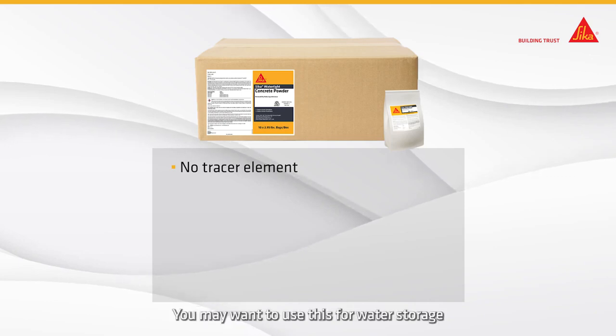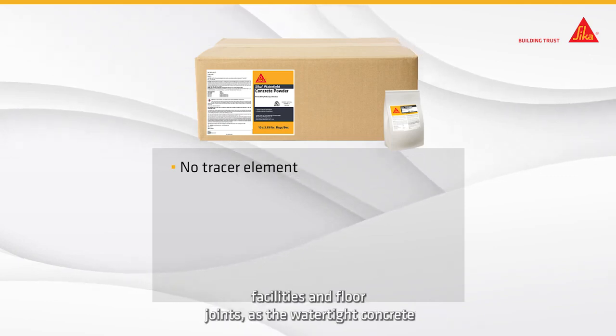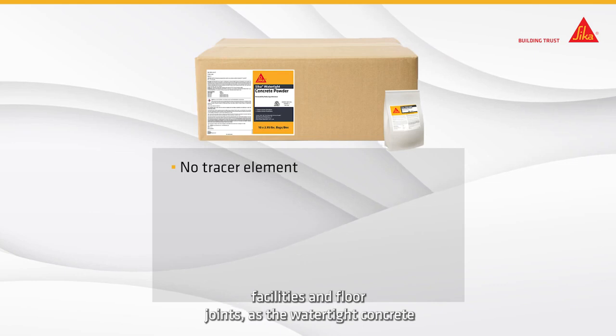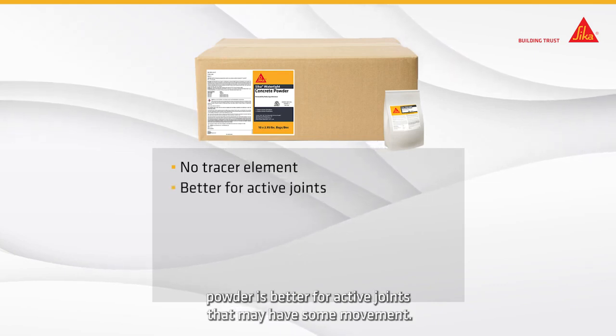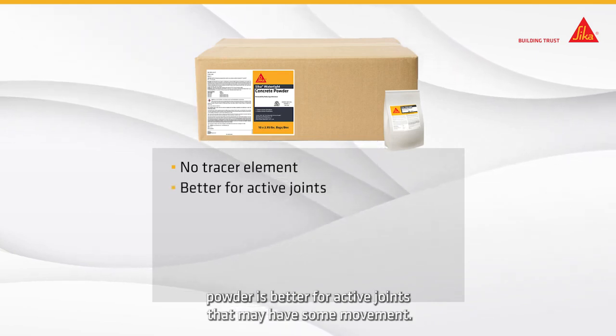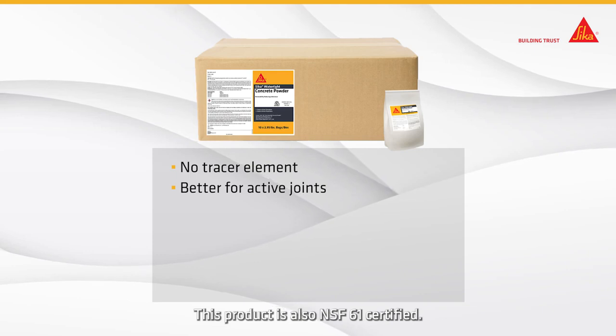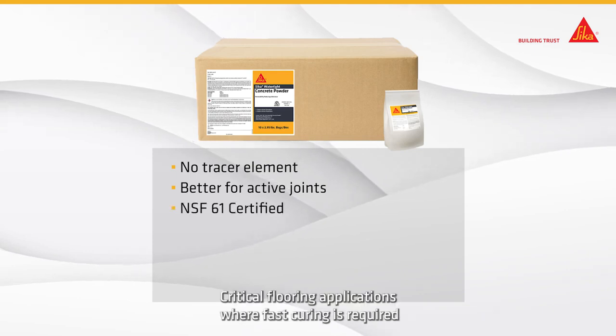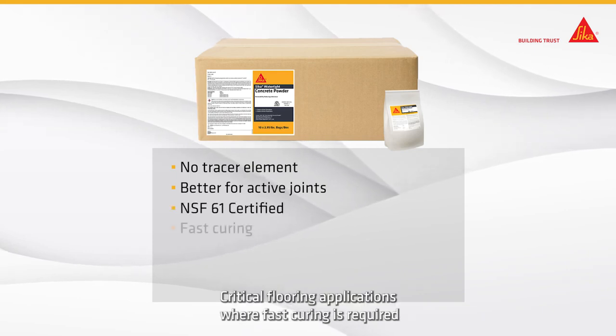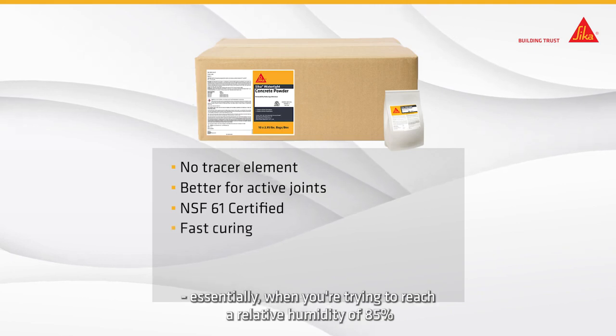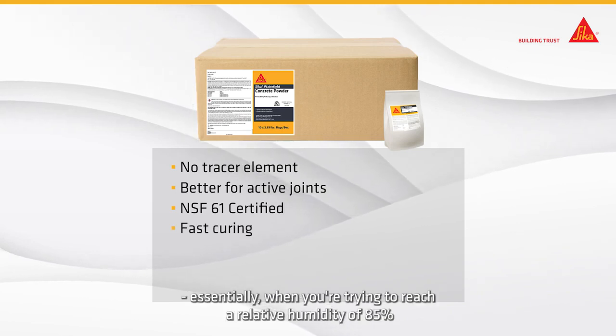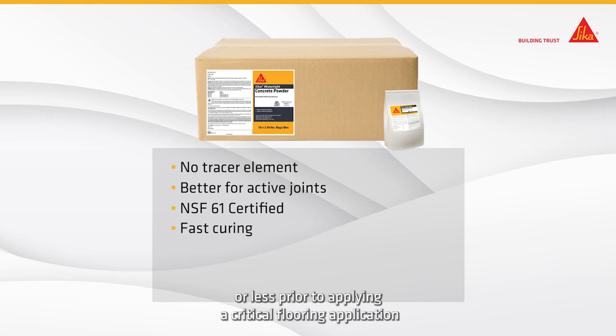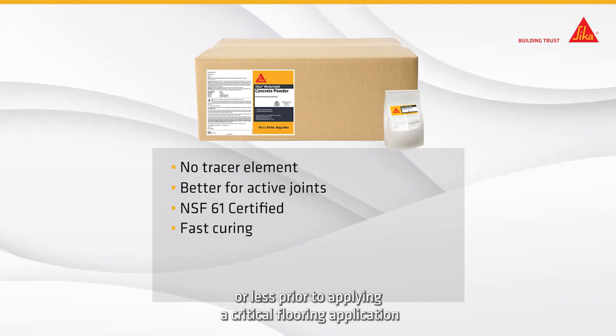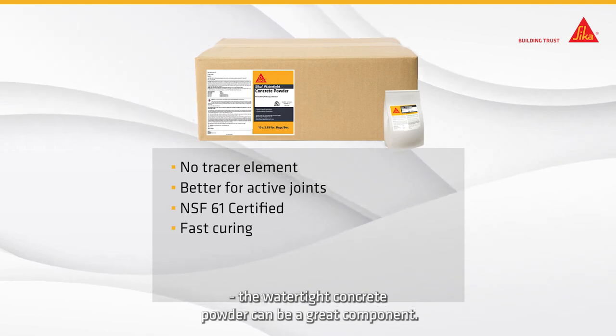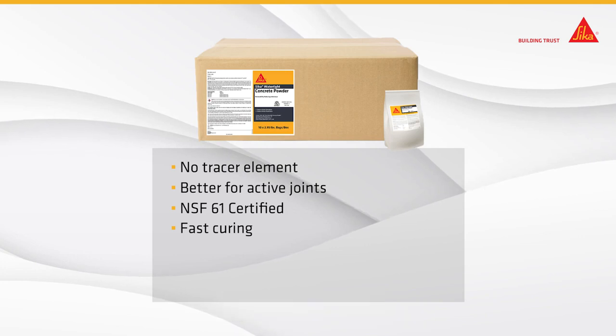You may want to use this for water storage facilities and floor joints, as the watertight concrete powder is better for active joints that may have some movement. This product is also NSF 61 certified. Critical flooring applications where fast curing is required, essentially when you're trying to reach a relative humidity of 85% or less, prior to applying a critical flooring application, the watertight concrete powder can be a great component.